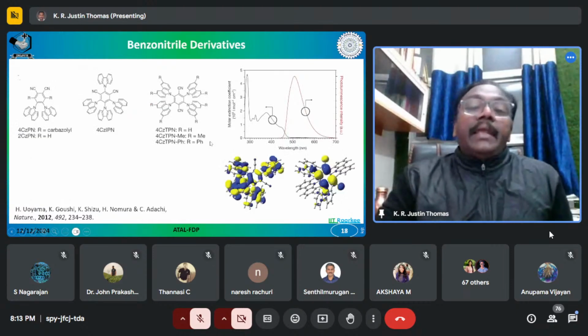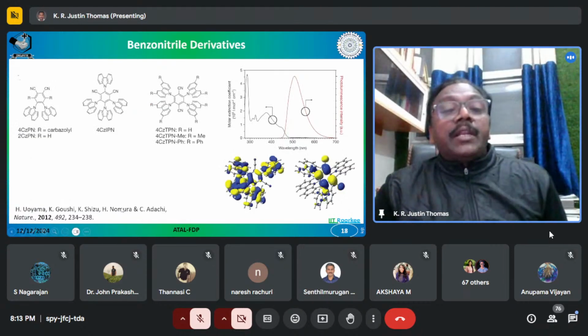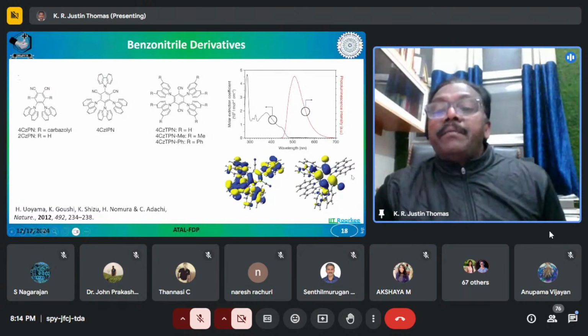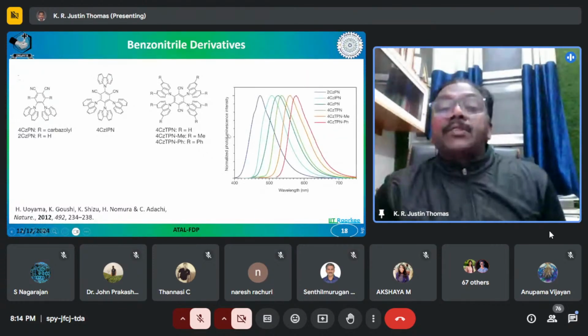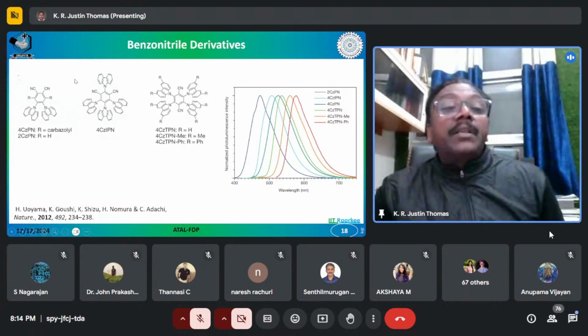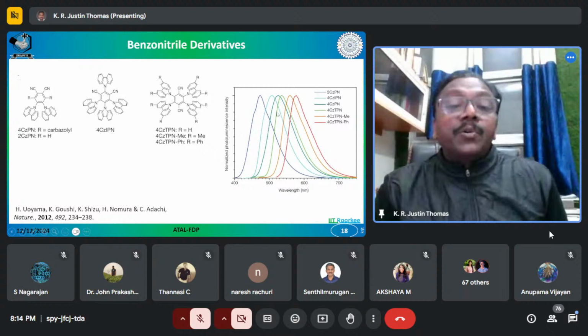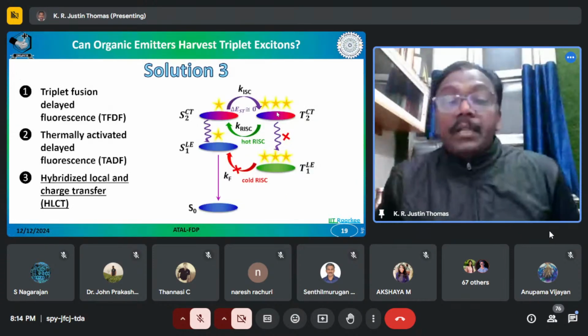Okay, but later the same group in 2012 reported, based on steric hindrance, several molecules designed on benzonitrile, and all these molecules showed reasonably well separated HOMO and LUMO, as shown here, and also showed charge transfer. They found that the emission of these molecules can be tuned by increasing the number of carbazoles. That is one of the good advantages of this molecule.